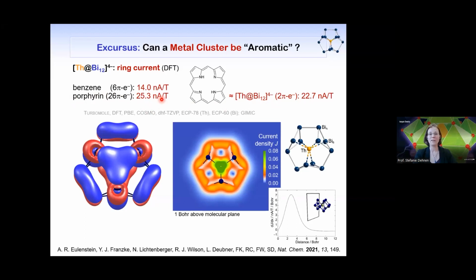Yet, if you compare these compounds, we just use 2 electrons to get this ring current, while for porphyrin, we need 26 electrons. So the same kind of ring current strength is obtained, summarizing that this is not only the largest known aromatic metal cycle, it also displays the largest, or the record 2n plus 4 pi aromaticity per electron. So there are stronger ring currents calculated, but not with just 2 electrons. So in the end, you can ask yourself, is that something special?